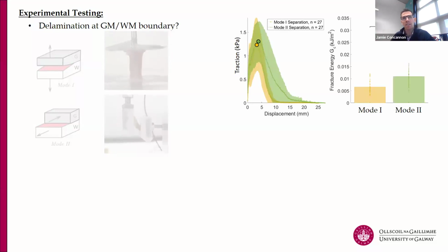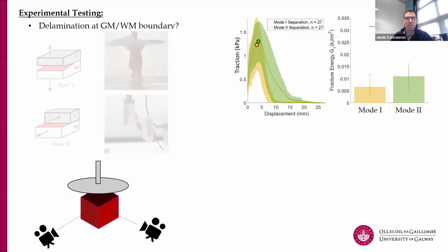But what is interesting is that the fracture energy is different. So you've got this more ductile behavior. Now this is a large strain analysis, so it's kind of an analogy, but you've got this ductile behavior of the green mode 2 separation, and you've got this brittle fracture of the mode 1. And we're trying to investigate whether at the boundary, this is a protective mechanism or not.